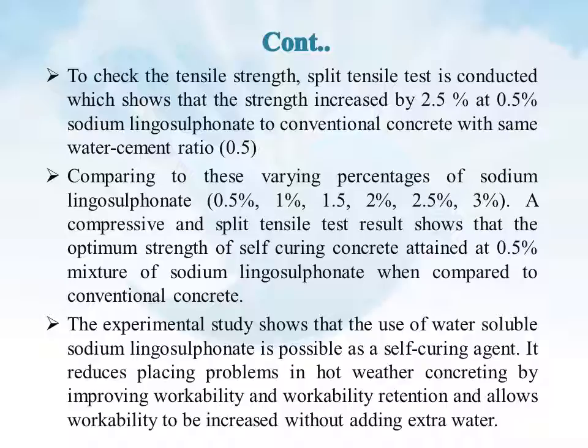Comparing these varying percentages of sodium lignosulphonate: 0.5%, 1%, 1.5%, 2%, 2.5%, 3%, the compressive and split tensile test results show that the optimum strength of self-curing concrete is attained at 0.5% of sodium lignosulphonate when compared to conventional concrete. The experimental study shows that the use of water-soluble sodium lignosulphonate is possible as a self-curing agent. It reduces placing problems in hot weather concreting by improving workability and workability retention, and allows workability to be increased without adding extra water.